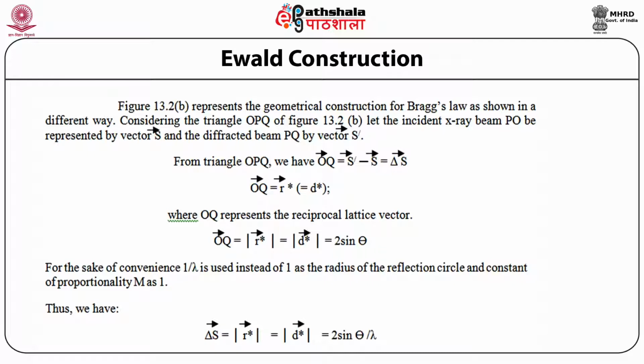From triangle OPQ, we have OQ vector equal to S prime vector minus S vector equal to delta S vector. OQ vector is equal to R star vector, which is equal to D star, where OQ represents the reciprocal lattice vector. OQ vector is equal to modulus R star vector is equal to modulus D star vector is equal to 2 sine theta. For the sake of convenience, 1 by lambda is used instead of 1 as the radius of the reflection circle and the constant of proportionality capital M as 1.